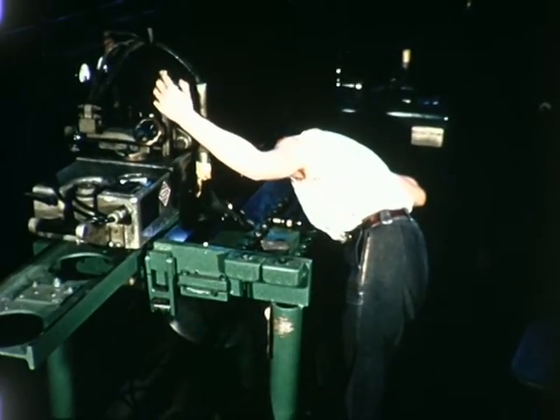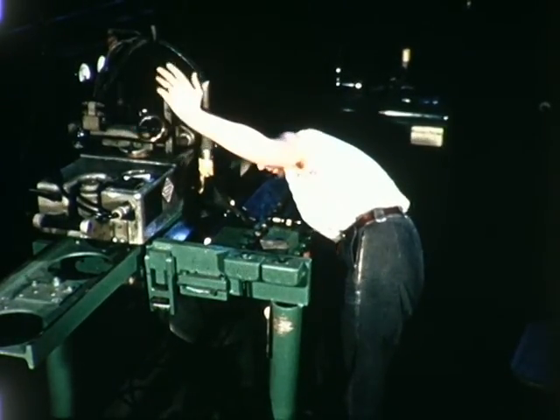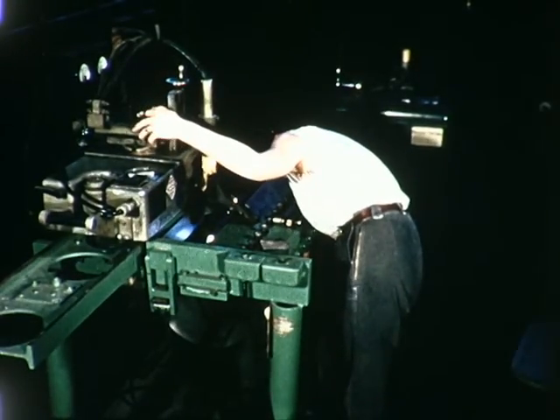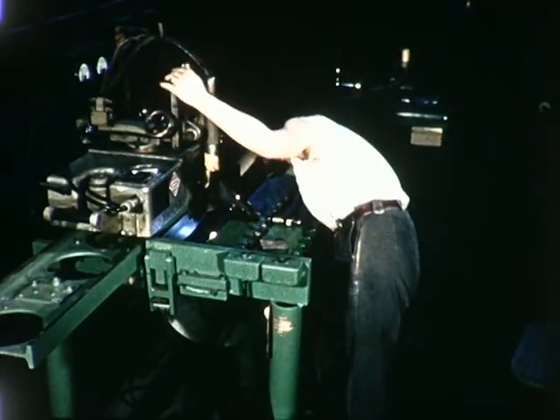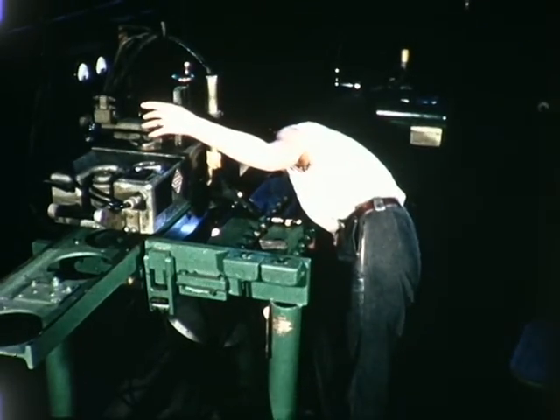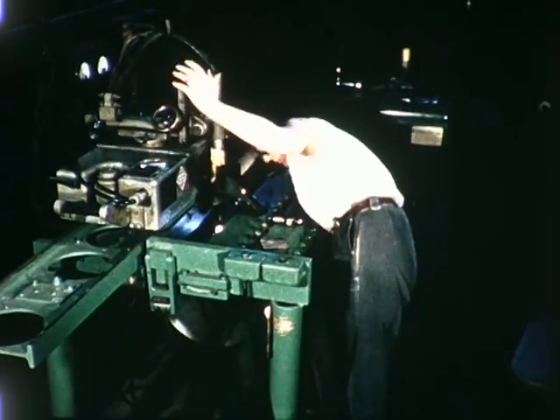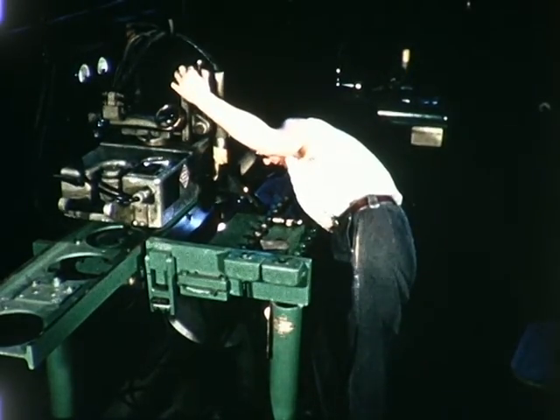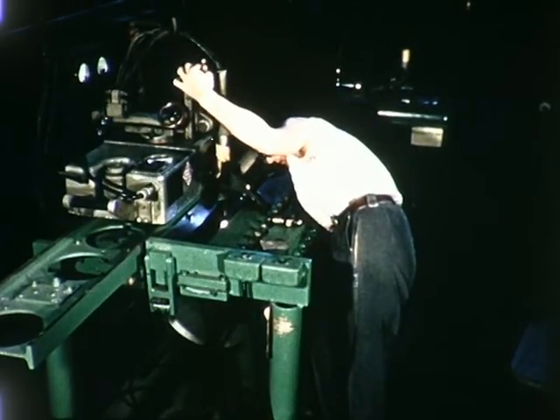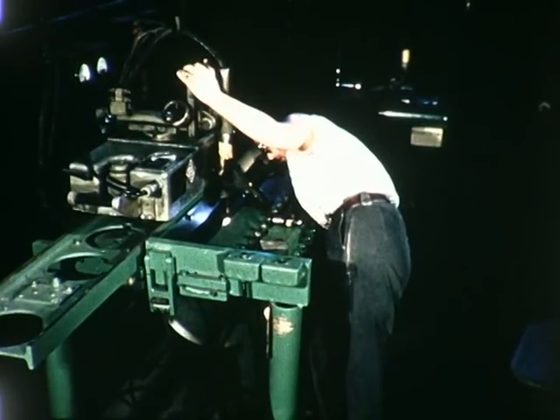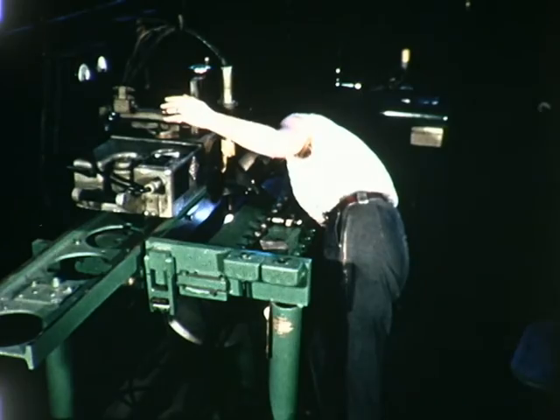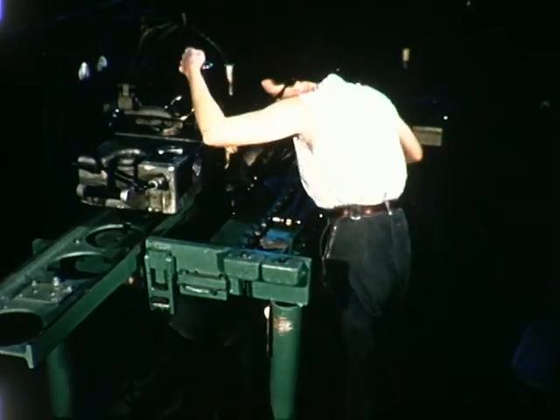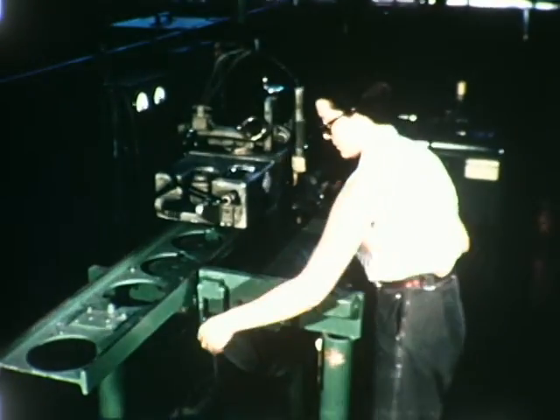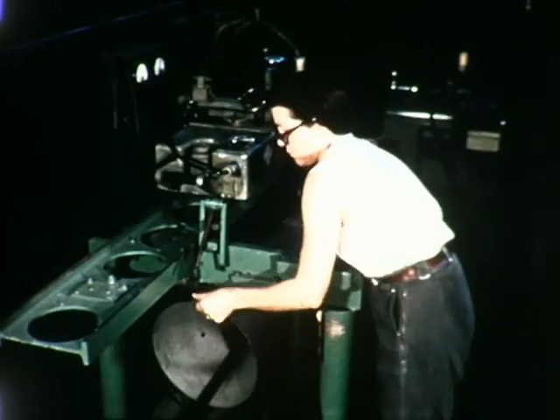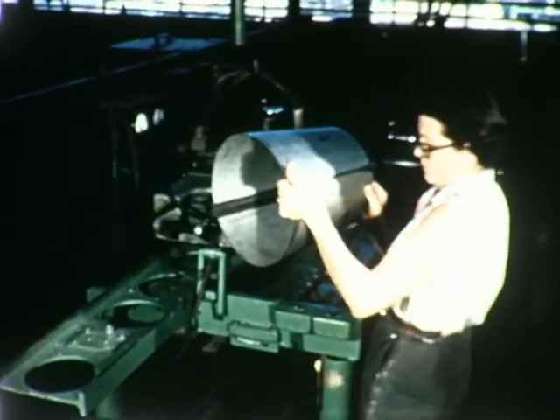Information at the present time indicates that welding should be done with the material in the solution-treated annealed condition. However, tests at Ryan indicate that this procedure is not always necessary. Automatic welding should be employed wherever possible for best results. To maintain our usual high standard of weld quality, all welds should be inspected by either the Zyglo or X-ray method. Assemblies will not be cleaned after the aging process. Where necessary, the loose scale may be removed from the weld with crocus cloth, a wire brush, or by vapor blasting to permit Zyglo inspection.